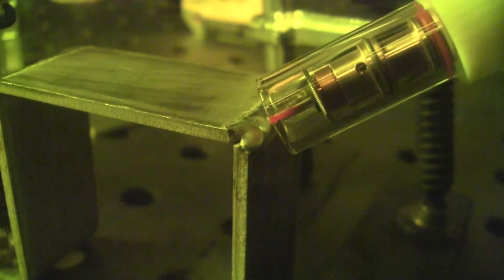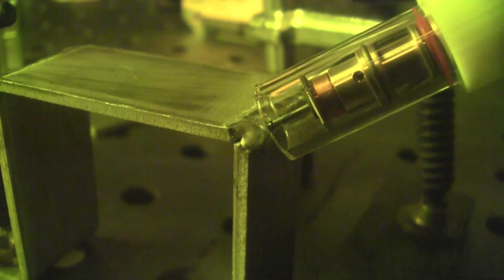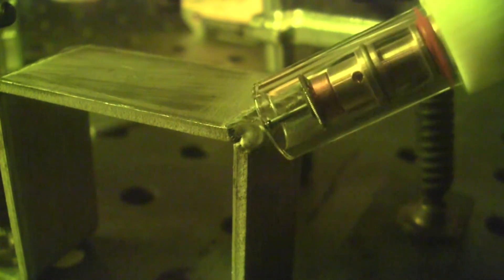And you'll see when I get to the end here it's not quite filled up. That's okay. That's not a sin. We just relight that arc and add a little bit more filler metal in right there at the end to make sure that it's full and we don't leave a crater crack or an area of depression there at the end of the weld that could cause it to crack at a later time.